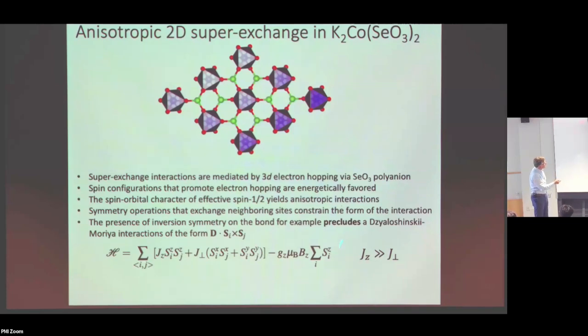And in our case, this one is 14 times larger than the transverse part. So it's not 100 times larger, which is good, because it's within our resolution. We can actually see the quantum fluctuations that result from this term.